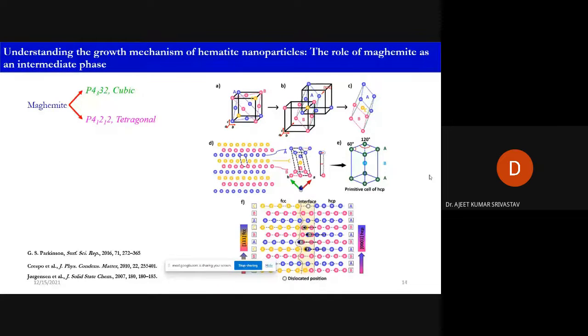With the level of vacancy ordering, if there is full complete vacancy ordering, then it will transform to tetragonal maghemite. So here tetragonal maghemite forms, and further, with slight dislocation or distortion, okay, we finally get the primitive cell of HCP. That is the E image that has been shown. And once the seed forms, then how the whole transformation proceeds, it has been shown as a schematic in subfigure F.